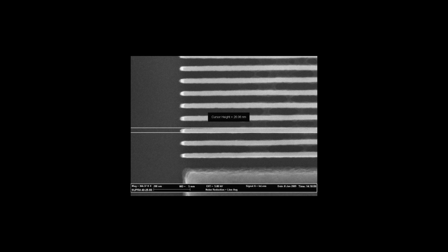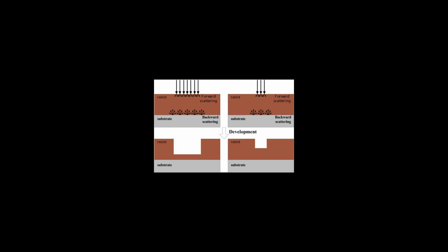A study performed at the Naval Research Laboratory indicated that low energy, 10 to 50 electron volts, electrons were able to damage approximately 30 nanometers thick PMMA films. The damage was manifest as a loss of material. For the popular electron beam resist ZEP 520, a pitch resolution limit of 60 nanometers, 30 nanometers lines and spaces, independent of thickness and beam energy, was found.